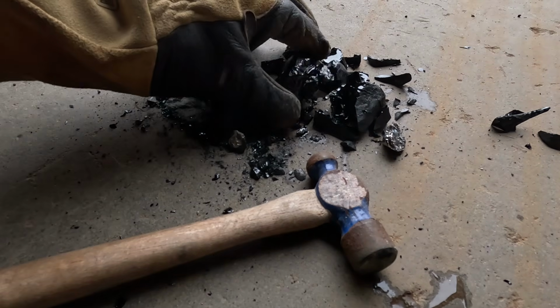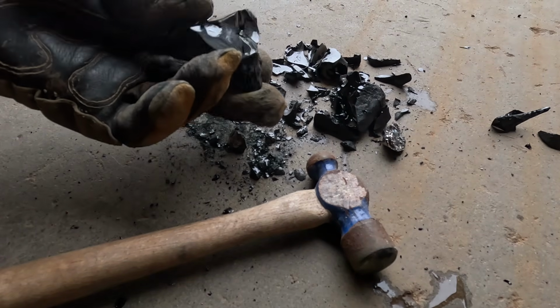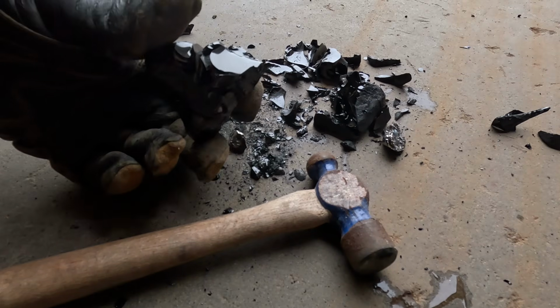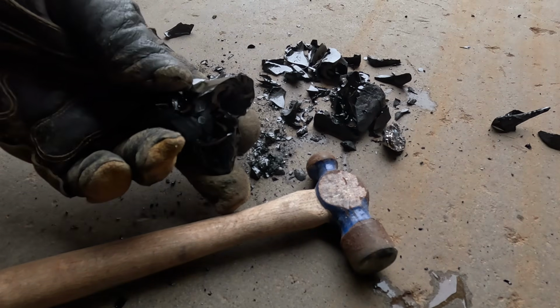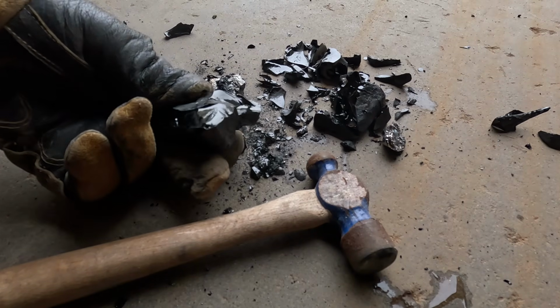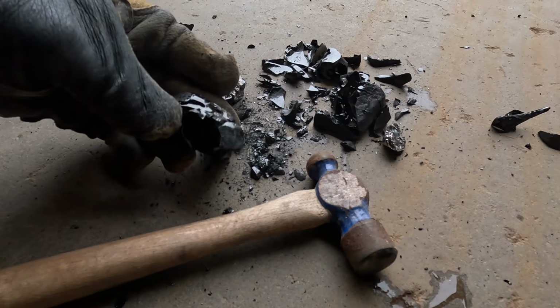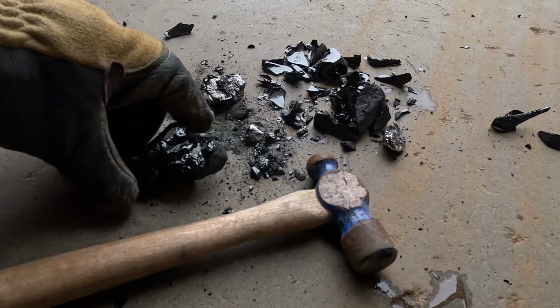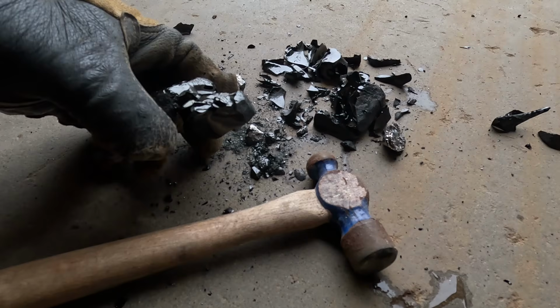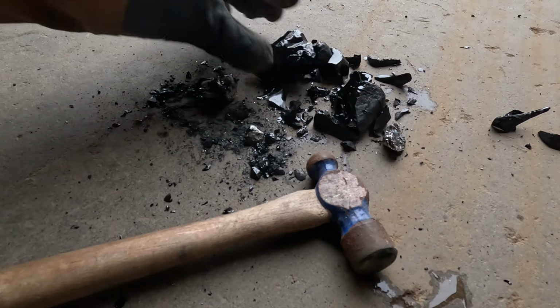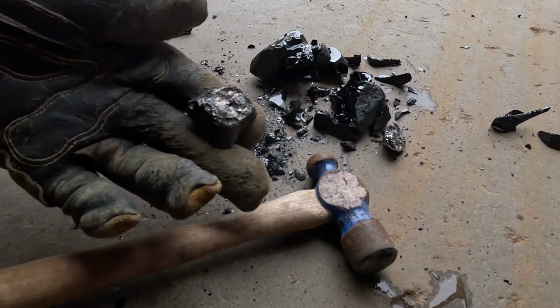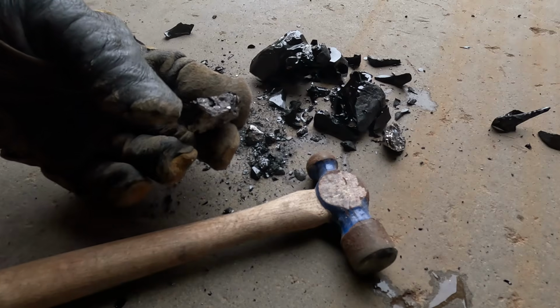The other thing I'm seeing here is this glass. The slag is so glassy. I think that happens when all the soda ash gets used up, essentially. And we don't have enough soda ash to absorb this iron sulfide.